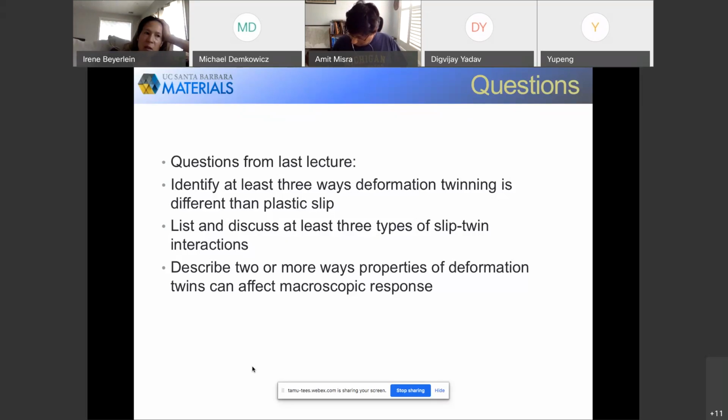So taking that idea and moving that to an HCP where you have a non-planar dissociation does also engender the idea that you can have a single dislocation be involved in producing one twinning partial, and then they sequentially glide on adjacent planes.